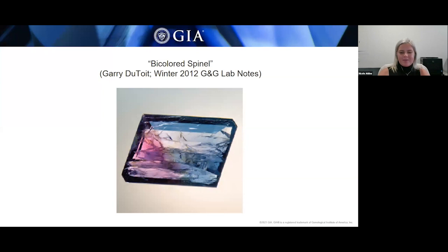So at the Bangkok laboratory, this 14.5 carat stone was submitted for examination, and it was bicolored with zones of blue and red. It had an RI of 1.718 and an SG of 3.6, confirming the stone was spinel. The red portion fluoresced medium red under long wave and was inert under shortwave fluorescence, and the blue portion was inert under long wave and shortwave UV.